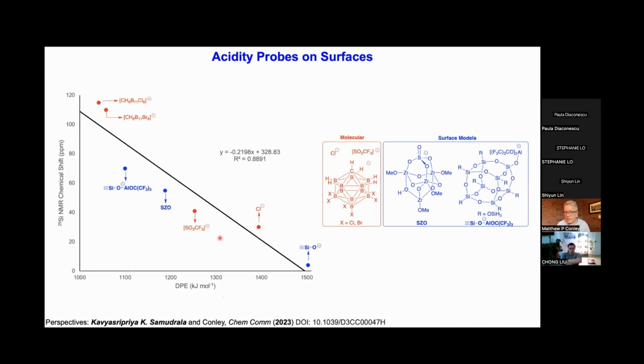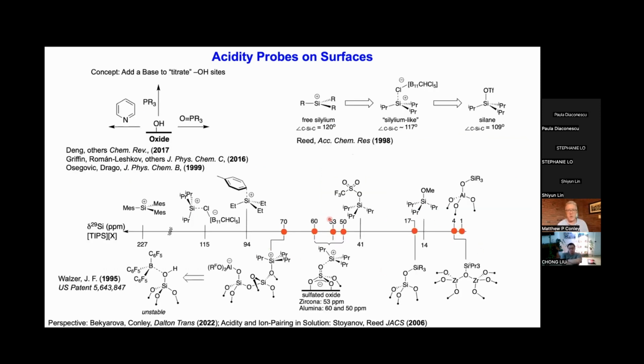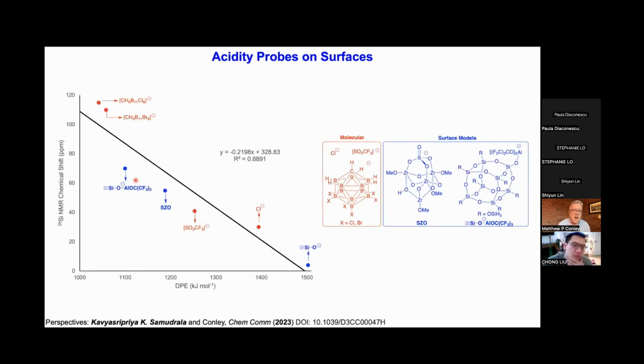So there's in fact a linear relationship, or kind of a linear relationship. I'll give you that the R squared is not great and we don't have a lot of points on this line, but this is also kind of early days in this area because we really don't have many points to see what the silicon NMR chemical shift is with respect to different oxides.